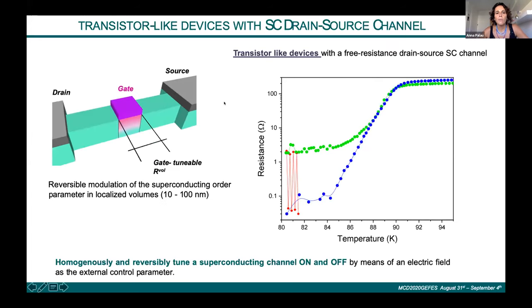But if we perform the same experiment in a four-point contact configuration, measuring the resistance between a source drain channel, what we obtain is that this is the TC of the starting material. And if we start from the superconducting phase, we can induce, by applying a voltage pulse, a transition to a non-superconducting state, and then come back to the superconducting state in a reversible way. This is the final system that we obtain after the pulses. So we are able to modulate this superconducting channel, to open and close the channel by applying these voltage pulses.